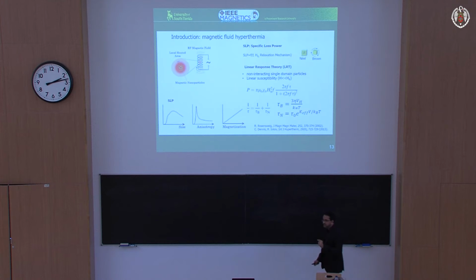Well, for health reasons, it should not be smaller than 10 nanometers, period. And the reason is because if you make very small particles, 5 nanometers or something like that, you have the possibility of these particles penetrating the blood-brain barrier and ending up in the brain, the wrong place where you want these particles to go. Ideally, you want these particles to treat the tumor, kill the tumor, and go down south to Florida, basically get flushed out of your system. So we don't want too small particles, because chances of them going to the brain is very high. Okay?